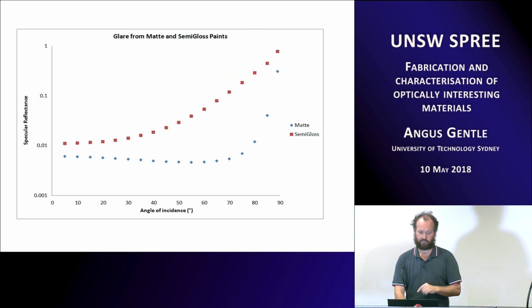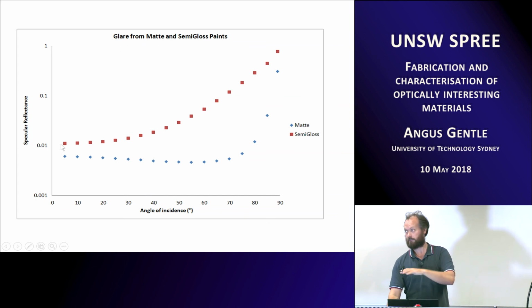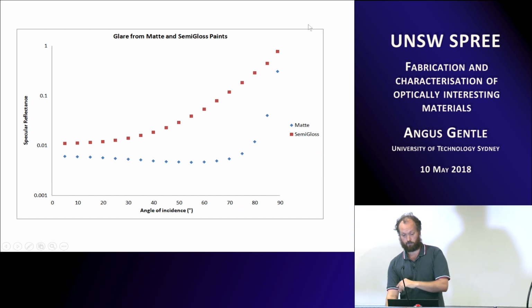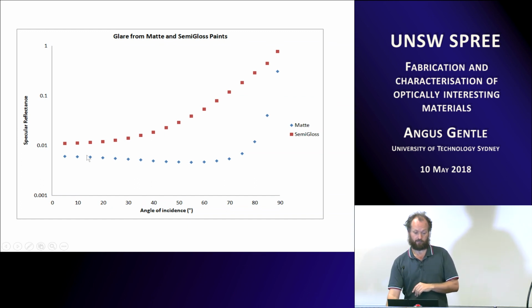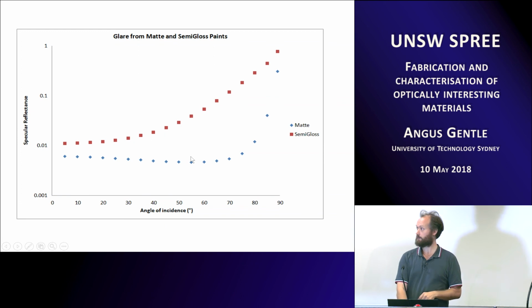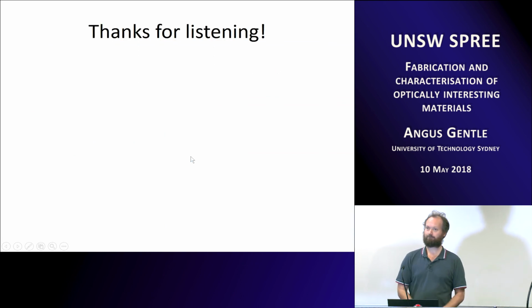So if you take that data there and then look at just the specular component, you can see that a semi-gloss thing, so this is not fully shiny, this is just like a Colorbond roof sort of level semi-gloss, goes up to quite high reflecting relatively quickly, and a matte surface actually does eventually start to go up as well, but it can be a lot lower. And so yeah, they're the sorts of different random measurements we do. And thanks for listening.